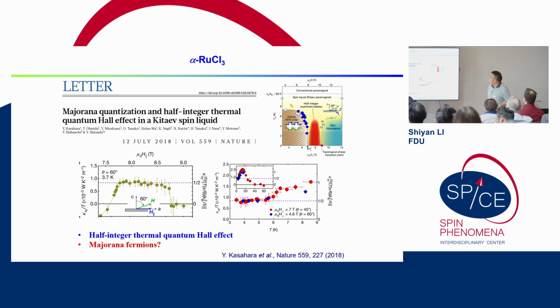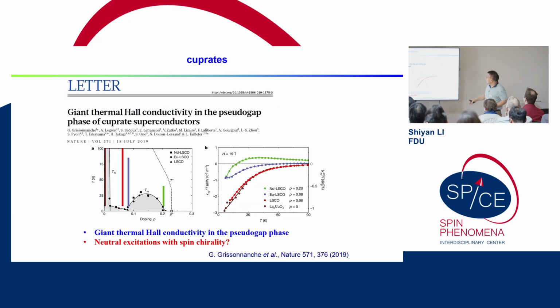Then there is the highly debated quantization of the half-integer thermal Hall effect in ruthenium trichloride. A lot of debate. You also saw this, from Louis Taillefer's group. So, to answer your question, giant means the absolute magnitude of the signal is much larger than in ruthenium chloride. Louis has a table, and the absolute value is very large. So they call it a giant thermal Hall conductivity.